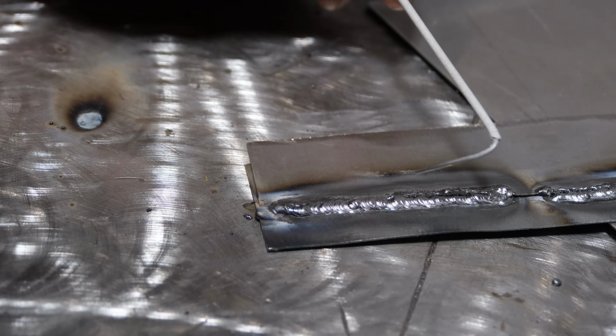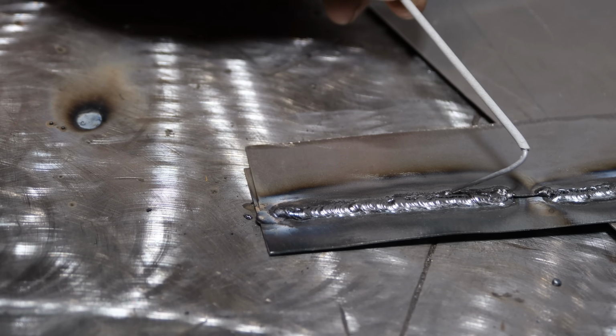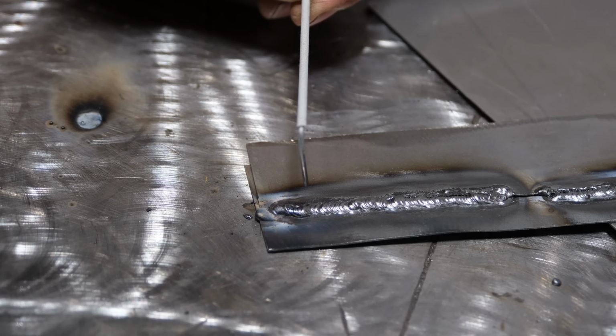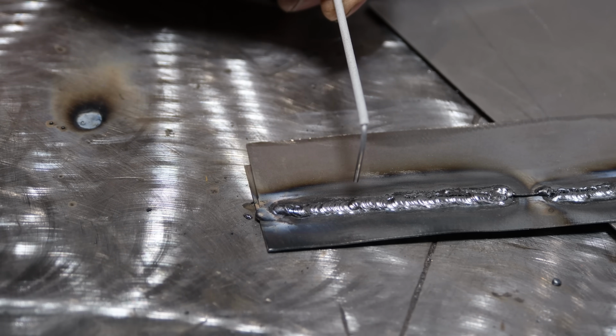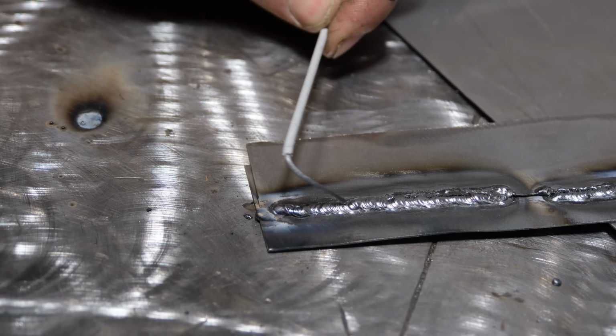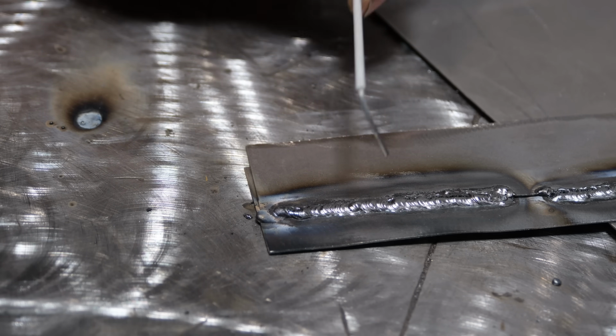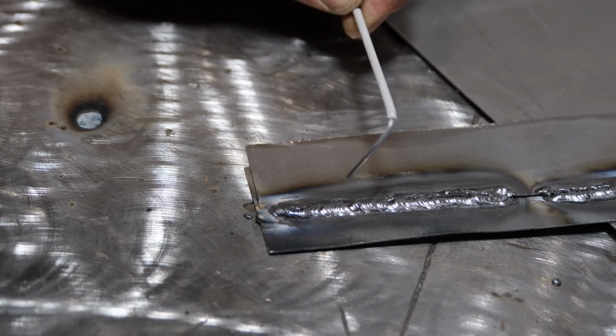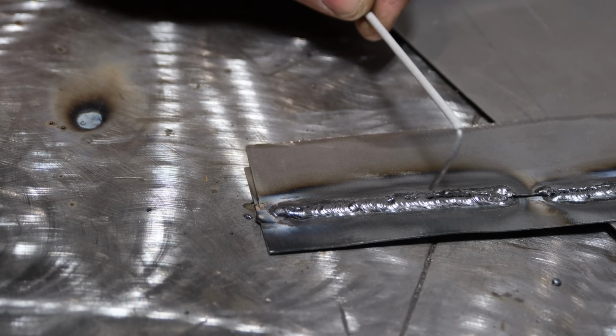This is 6013. There's still some slag I didn't clean, I see there. This was easier to weld as far as not blowing holes. The problem is this rod likes to stick. At 25 amps, it just wasn't enough. It kept sticking the rod. I'd have to restart. Here's a disaster of the second one that I tried.